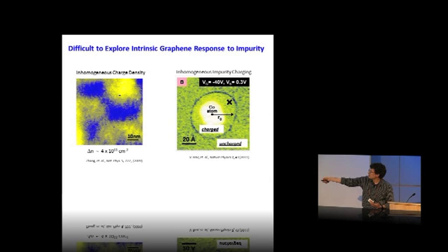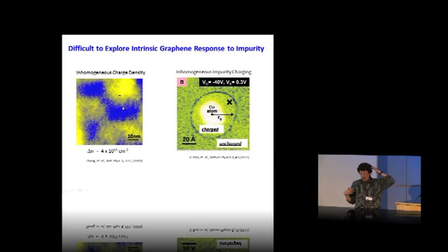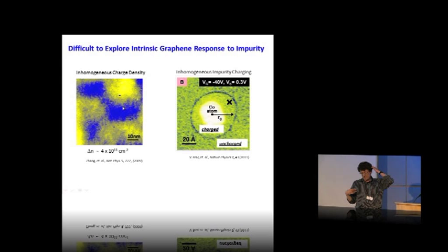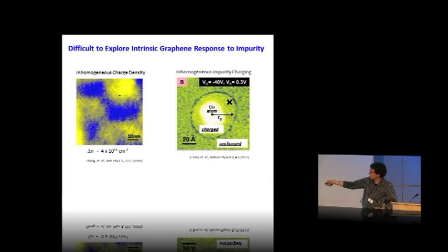One of the things we'd like to do with this capability is investigate what happens in the vicinity of Coulomb potentials on graphene — measure around these charge impurities to see what the electrons are doing. But we have problems. The graphene on silicon oxide is very inhomogeneous. This electronic inhomogeneity obscures what's happening around a single atom, because any charge distribution around that atom due to the Coulomb impurity gets obscured by the charge inhomogeneity.